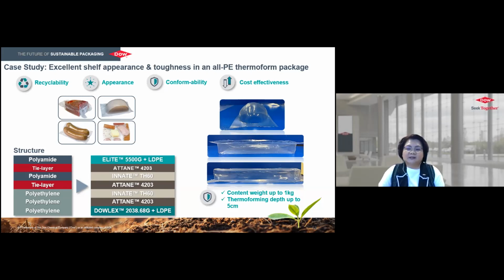articles. Although Dow has retained the polymer modifier to recycle such articles, the most straightforward way is to design monomaterial structures for easy collection and also send for recycling. Thus, we hereby introduce to you Dow's solution for all PE thermoforming films, as seen on the bottom left. This solution allows one to achieve a draw depth of 5 centimeters while maintaining excellent formability and balance of toughness and shape retention. The image on the right demonstrates the edge and shape stability after thermoforming, resulting in excellent appearance to the end users.